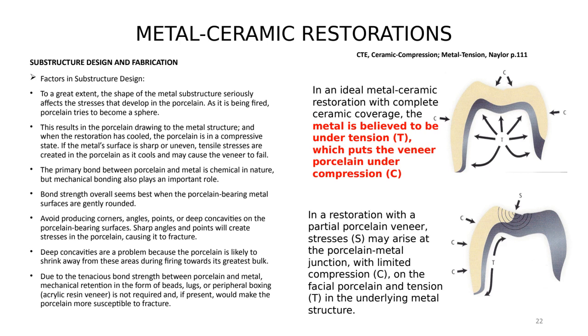Factors in substructure design: to a great extent, the shape of the metal substructure seriously affects the stresses that develop in the porcelain. As it's being fired, porcelain tries to become a sphere. This results in the porcelain drawing to the metal substructure, and when the restoration has cooled, the porcelain is in a compressive state. If the metal surface is sharp or uneven, tensile stresses are created in the porcelain as it cools, and it might cause the veneer to fail.